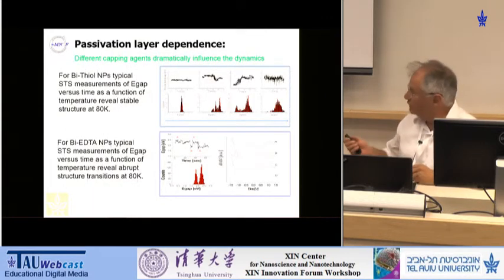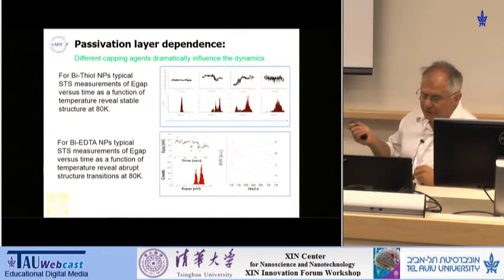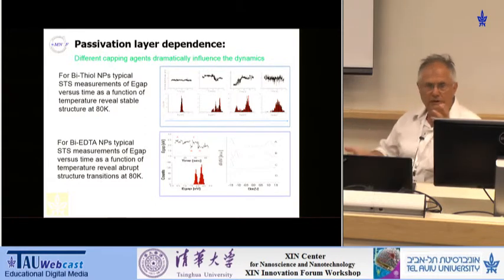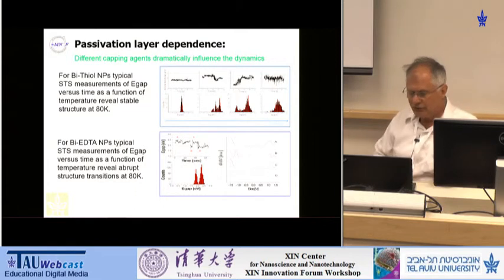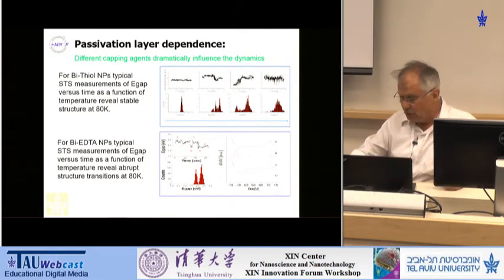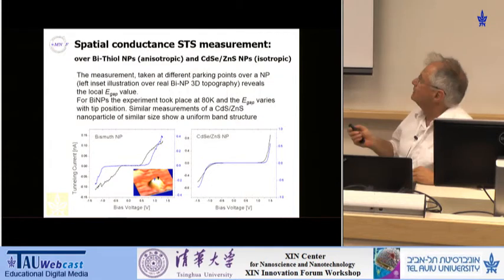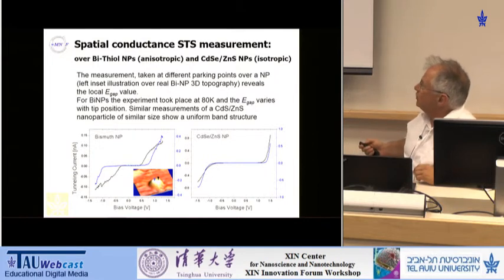Now one can control in a way the rate of these changes. If you coat the nanoparticles with different coatings, protection layers, then those particles can slow down or accelerate this rate. One can see furthermore that not only does the particle change its properties, but if we record a particle in different locations at very low temperature, where it's relatively stable, then on two different faces of this particle one would observe two band gaps, like what you see here. You see one gap which is small and one gap which is wider.